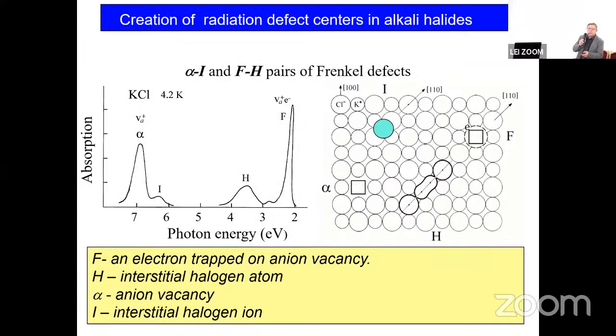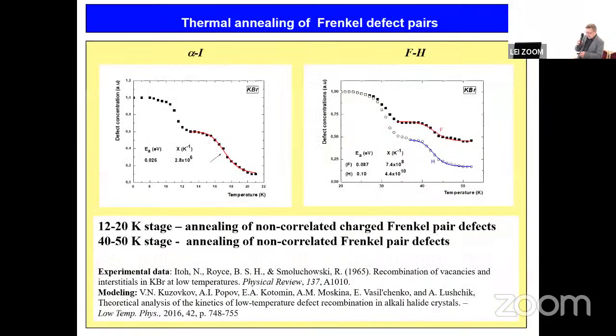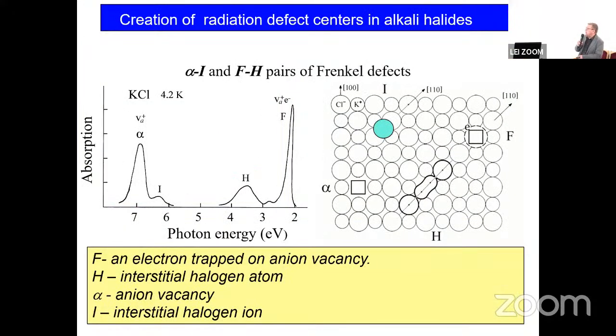We always need to test the model against some well-known and well-established experimental results. So we use this model to evaluate thermal annealing of point defects in alkali halides. Just an example of that: you can see what type of point defects, charged and neutral. You can see a vacancy with an electron, and two types of interstitials.